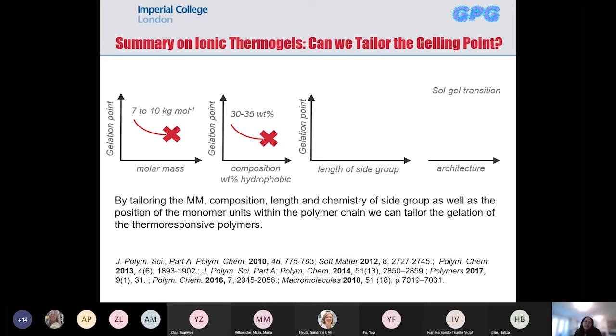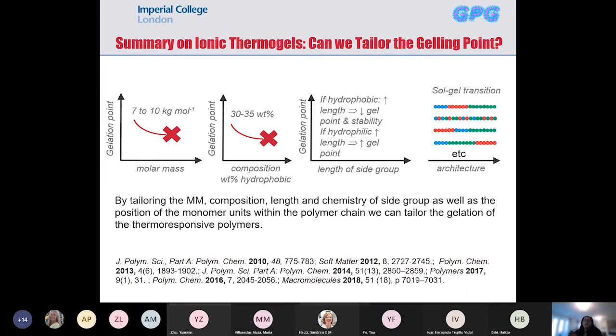In terms of the length of the side group, it depends if that side group is hydrophobic or hydrophilic. So if it's hydrophobic, you're lowering the gelation point. If it's hydrophilic, then you're increasing it. And then the architecture, that was something that we were very much interested to prove, that the architecture will have an effect. We have always concluded that the ABC structure with the B hydrophobic component in the middle was the one that was making our best gels.